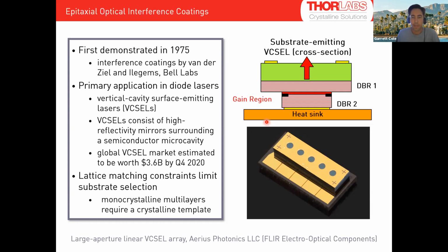come from. I think many of you are familiar with these, but if you're not, this in cross section is an interesting microcavity laser structure where you have two interference coatings or two high reflectivity Bragg stacks with a very thin gain region in between. So it's a relatively high finesse cavity for a laser. The laser light rattles around between those two Bragg mirrors and emits normal to the surface of the wafer.